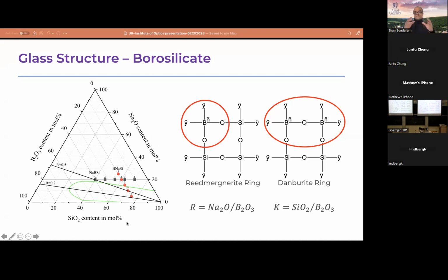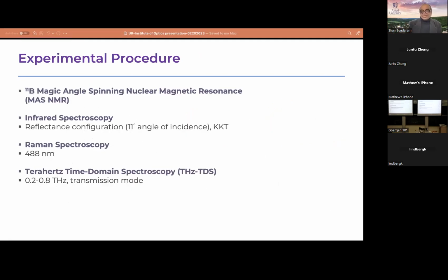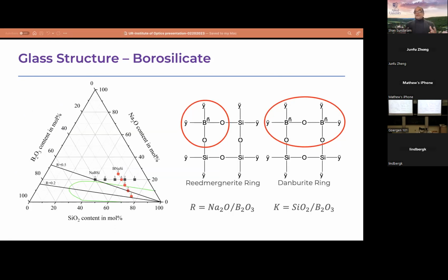The silica we call the backbone structure. When you melt silica and quench, you form silica tetrahedra inside the glass. The sodium oxide, or alkali or alkaline earth, we call modifiers. What they do is break some of these oxygen-silicon bonds, making a non-bridging oxygen, in the process depolymerizing the glass structure. And boron plays a double role. It partly associates with the silica tetrahedra, and partly likes to be on its own. So it's an interesting mixture of glass structure you get. Finally, you get a range of glass structures.